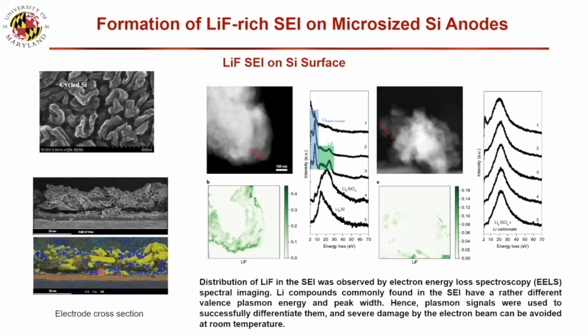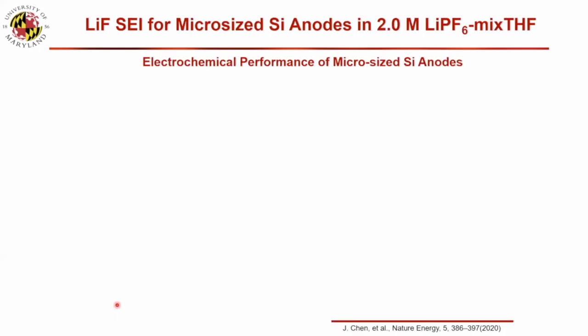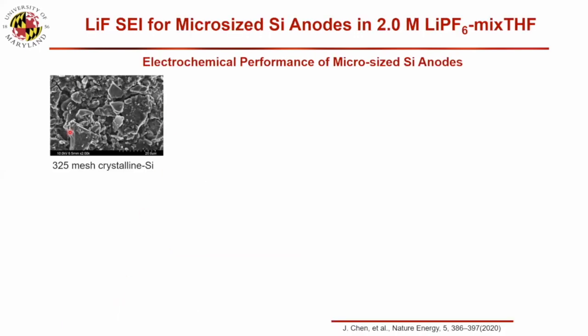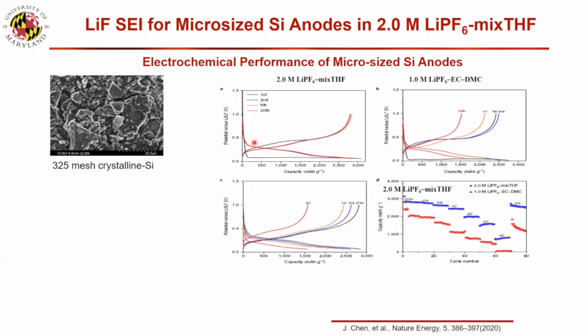So this is the cross-section of the silicon electrode. We just bought the silicon from Sigma-Aldrich, 325 mesh. We did not do any treatment, and we just put in electrolytes and cycled. So this is the THF electrolyte, different cycles. They are really stable. But with the traditional electrolyte, at different cycles they quickly decay.